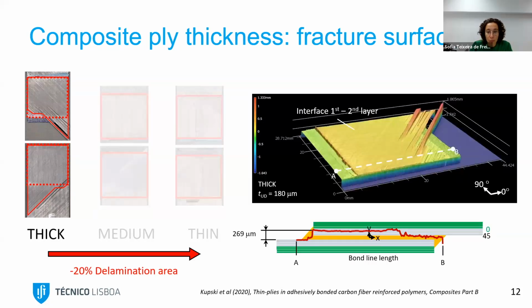So we had a 20% decrease in the delamination area when we decrease the thickness. If we have a closer look into the fracture surface, what we see here is a 3D profilometer of the fracture surface, so we have a topography of the surface. For the thick, we see that the fracture surface mostly traveled within the first and the second layer, so always within the 45 degrees angle or in between these two. But the crack didn't travel a lot within the composite, so it was quite flat.